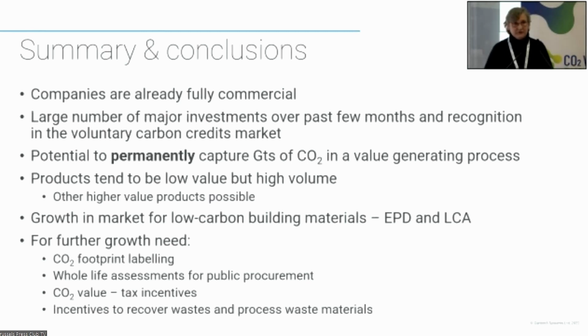So it's a good commercial enterprise. There are many companies that are already fully commercial, TRL 9, and those companies have had major investments over the past few months and recognized in that voluntary carbon credits market. An important thing, we can permanently capture gigatons of CO2 in a value generating process. So to capture a ton of CO2 in our process, you can make €200 rather than it costing you. Products tend to be low value, high volume, lots of growth, and we must be looking at environmental product declarations and LCAs to prove the carbon credentials of the materials and those things that we need to do as well.